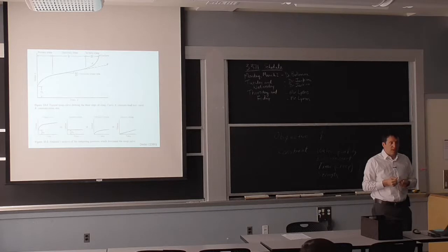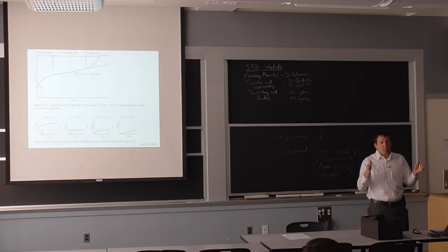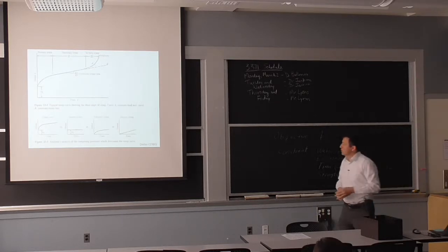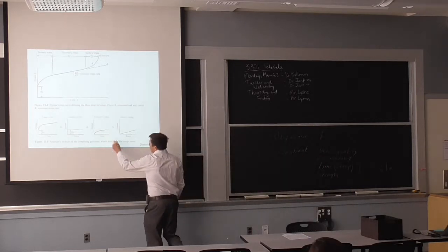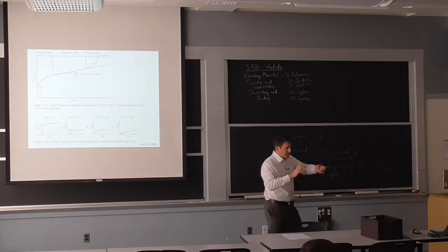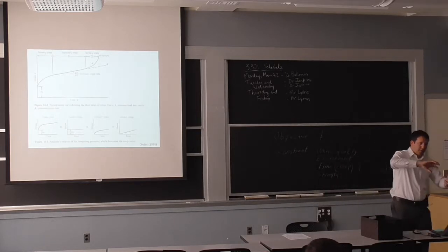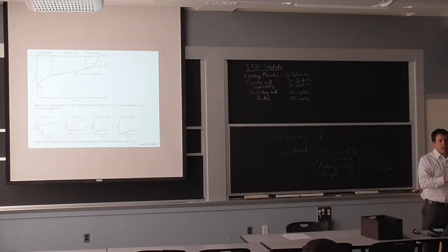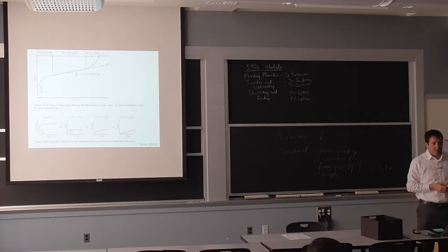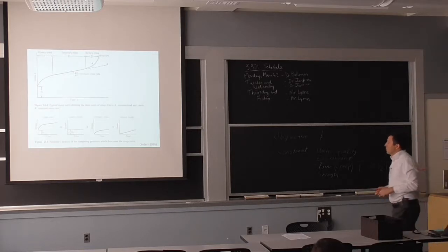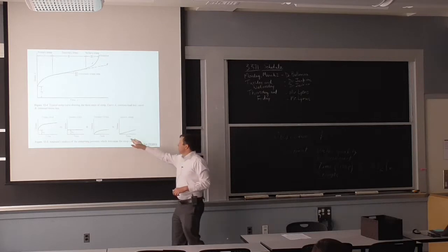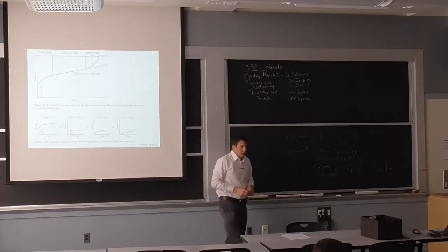It's a very, very slow rate, and it starts right from when you apply the load. You don't really see it at the beginning. What you see is this transient creep where it's actually big segments of the chains rotating around themselves to allow each other to move, and you can generate sometimes as much as 10–15% strain through that process. And when you're done with this, now all you can do is really move one chain with respect to the other. It's a slower process, but at that point it becomes time dependent with respect to the rate. So here it's pretty constant.